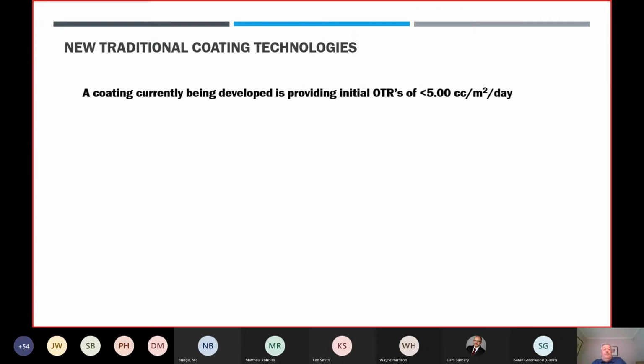So we have new, non-traditional coating technologies steaming down the track. I'm currently working on a coating that's been developed, and it's providing an initial OTR of 5 cc per meter squared per day. And this is the initial start point. And we believe that we can get very, very much lower than that level in terms of transmission, but higher in terms of barrier.